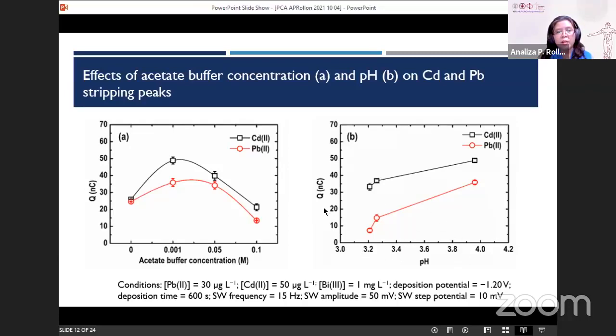We have here the stripping peak area versus the pH. And as we can see, as pH increases, the peak area also increases. However, we did not determine any more beyond 4 because we take note also that beyond 4, there can be complexation of the metal ions, for example, lead, and that can be not good for the analytical determination of the metals.